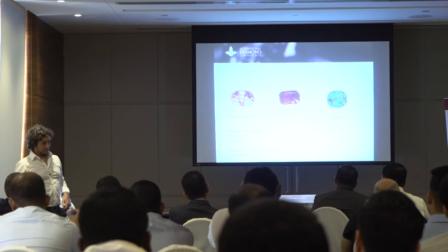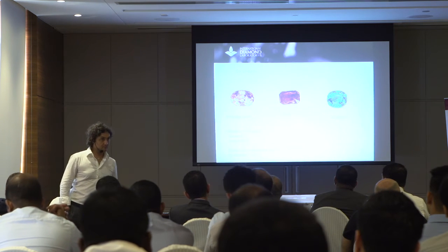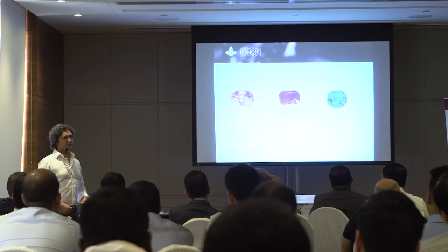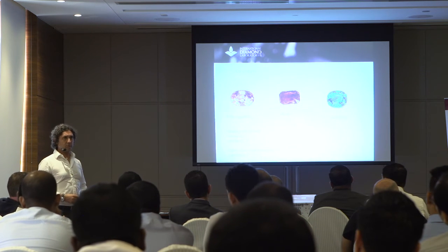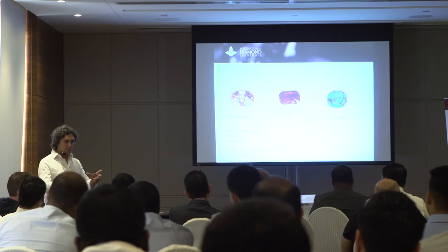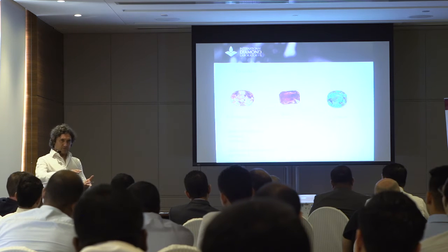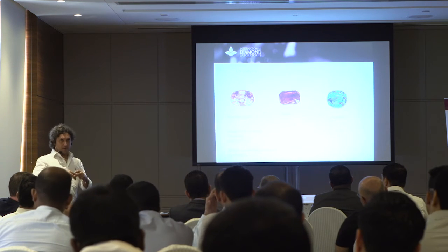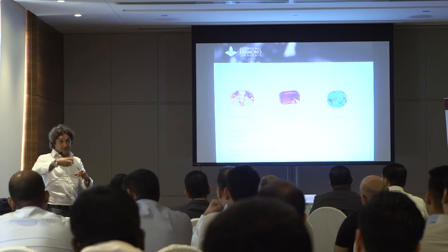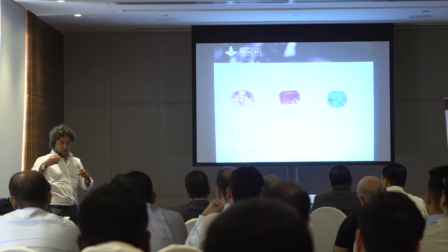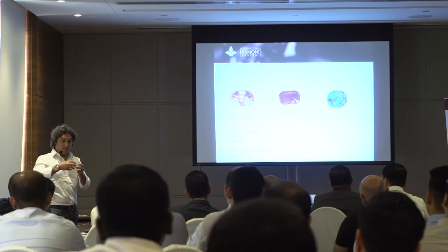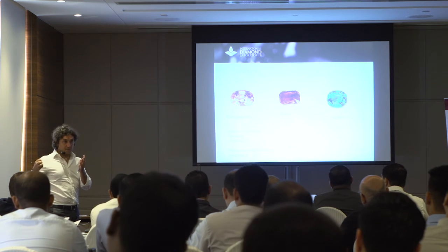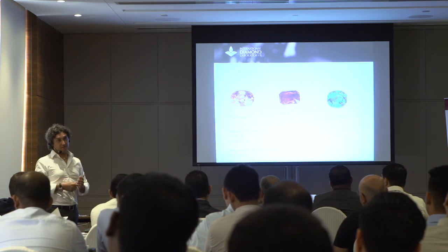These are easy to do, they're cheap processes? Expensive? Yeah, no. This is not anything really complicated. It's a vacuum. It's a small vacuum pump because you need to suck the air out of the cracks. Once there is vacuum in the cracks, you inject the oil and it will be sucked in.